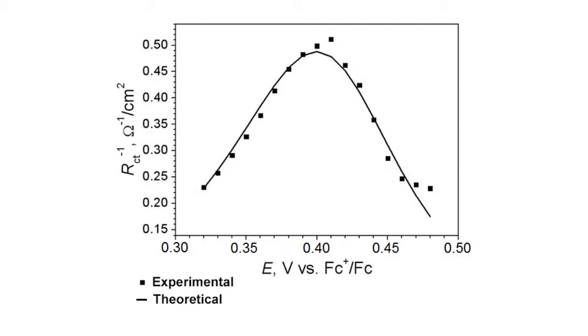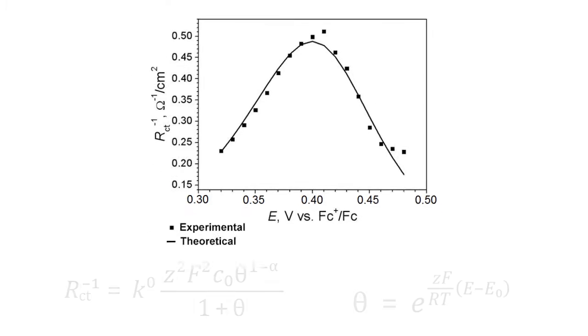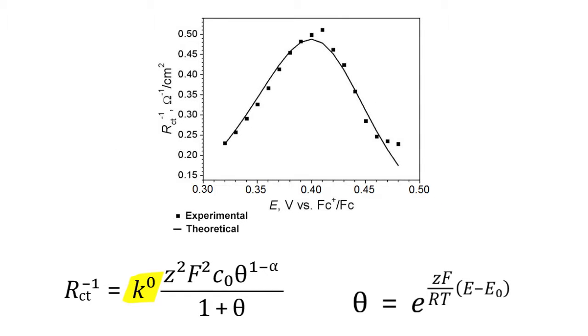The inverse charge transfer resistance values were plotted with respect to electrode potential versus ferrocene, along with the theoretical dependence of the inverse charge transfer resistance on electrode potential. The standard electrochemical rate constant was then estimated by varying the equilibrium potential and the rate constant until a reasonable fit for the experimental data was achieved.